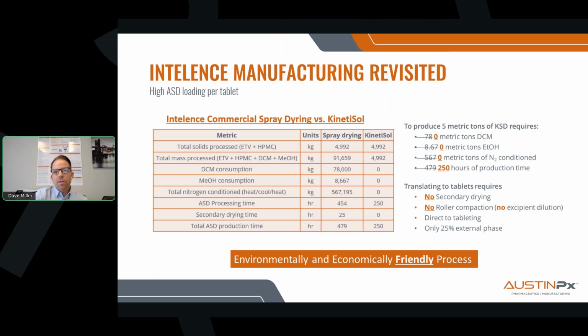And once you have the KinetiSol material, it's, as I said, ready for direct compression. There's no residual solvents to dry off. There's no need to densify through granulation, and it only requires minimal external excipients to convert to a tablet with good disintegration and tensile strength. And obviously, from an environmental standpoint, we go from hundreds of tons of solvent to none, which is highly ideal. And from an economic standpoint, we're cutting process time, material use, and energy by a substantial margin. So when you take all of these changes together, these make KinetiSol both an economically and environmentally very friendly process, and far more sustainable for commercial manufacturing.